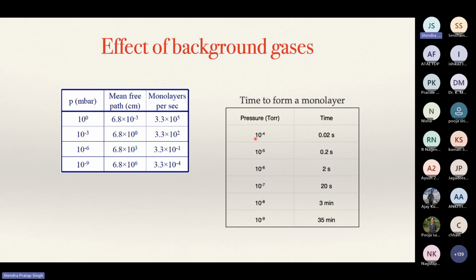If my chamber pressure is 10 to the power -4, then it takes only 0.02 seconds to form a single monolayer. If I go for 10 to the power -5, normally we work here like normal lab vacuums are 10 to the power -6, which you can easily get. So it takes only 2 seconds to form one monolayer. These numbers are just typical numbers, not exact. So one monolayer, meaning you want to deposit, takes only 2 seconds.